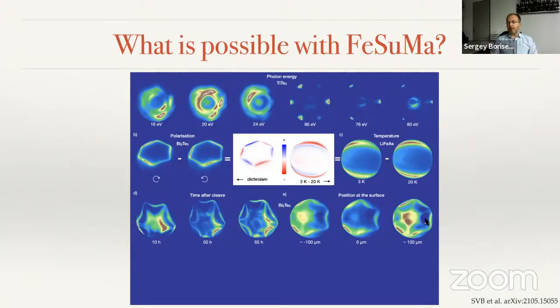Also important, the position at the surface. It turned out that even the perfectly looking cleaved surface of, in this case, bismuth telluride, visually gives you the possibility to see that when you move the sample only a little bit, the Fermi surface is actually different. In this case, you moved it by a couple of microns. You can by 10 to 100 microns, and you see that the Fermi surface is different.